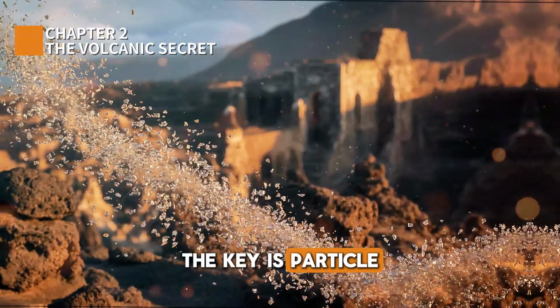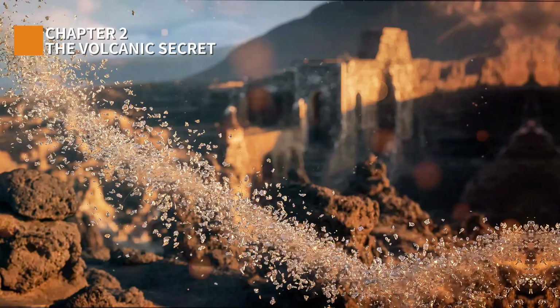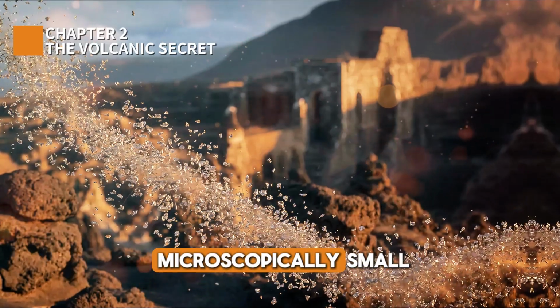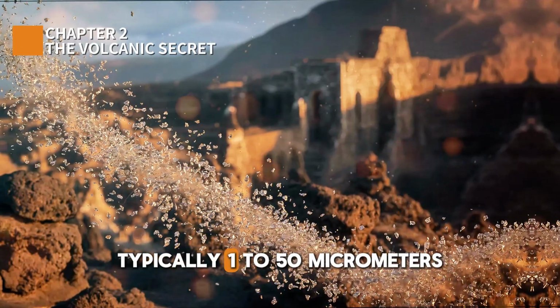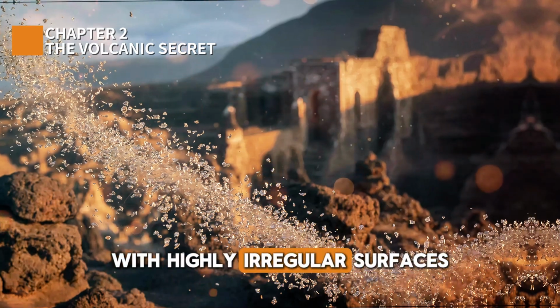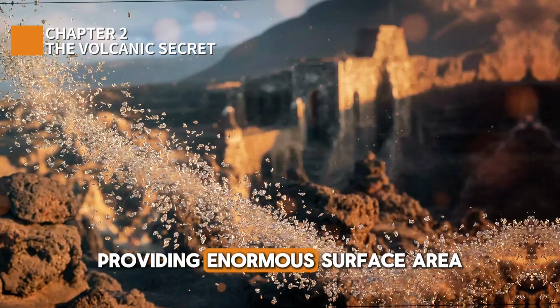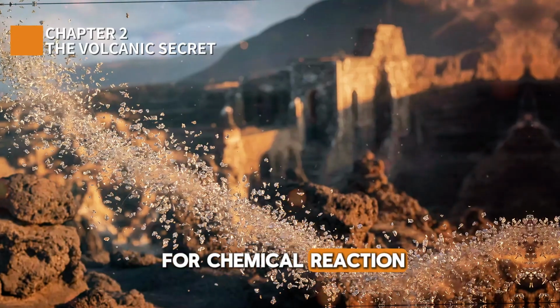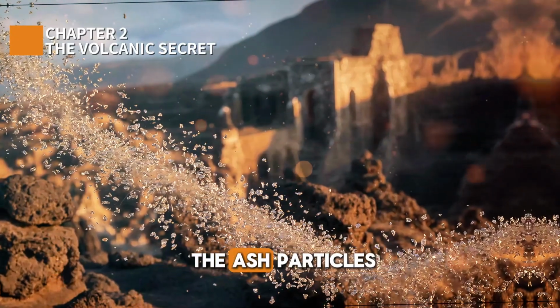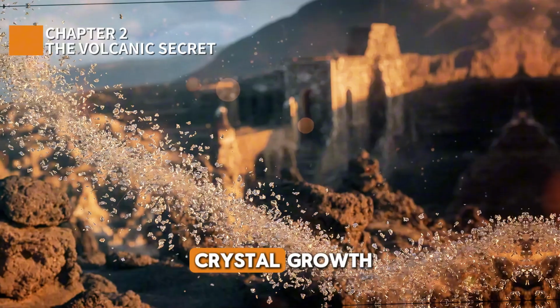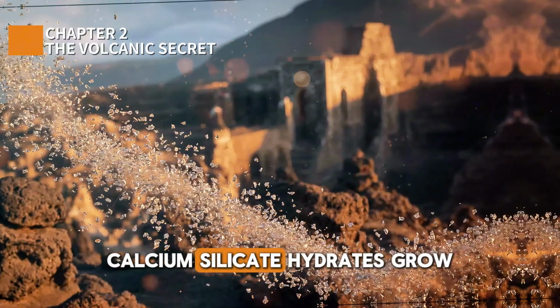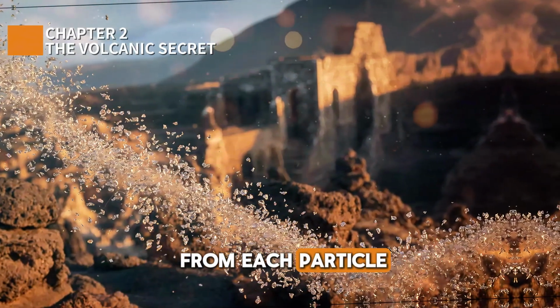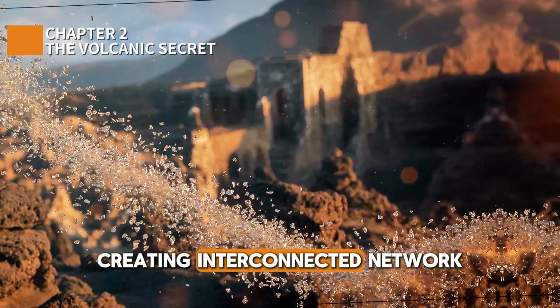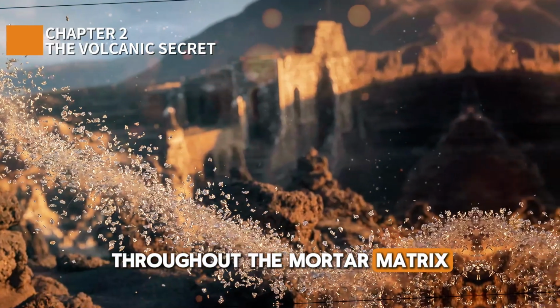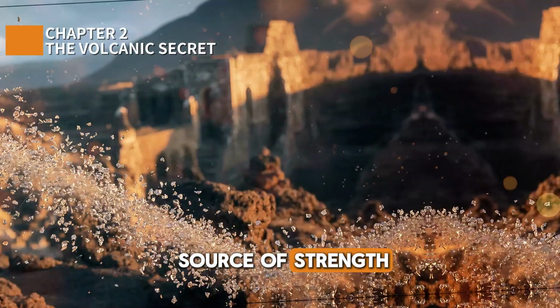The key is particle size and reactivity. Volcanic ash particles are microscopically small, typically 1 to 50 micrometers with highly irregular surfaces, providing enormous surface area for chemical reaction. When mixed with lime, the ash particles become nucleation sites for crystal growth. Calcium silicate hydrates grow from each particle, creating an interconnected network throughout the mortar matrix. This network is the source of strength.